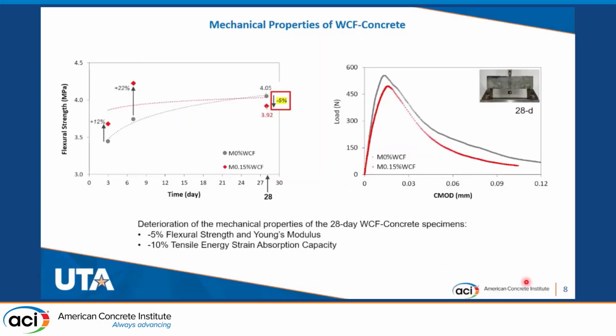We developed waste cellulose fiber concrete mixtures in our lab, and we tested a variety of waste cellulose fibers. In this slide, I am showing you the results of the mechanical properties of mortars, concrete reinforced with one type of fibers, waste cellulose fibers derived from this pulp with straw at an amount of 0.15% per weight of cement. From the rate of the flexural strength development shown in this graph in the left part of this slide, we observe that addition of fibers increases the flexural strength at the 3 and 7 day specimens.